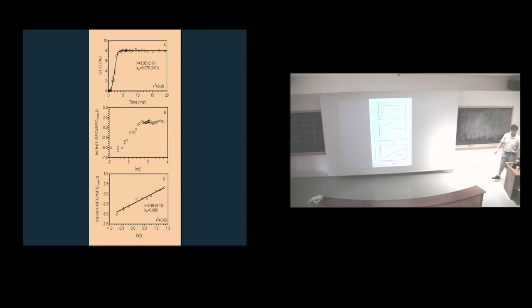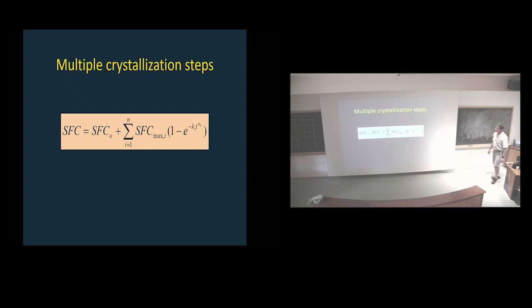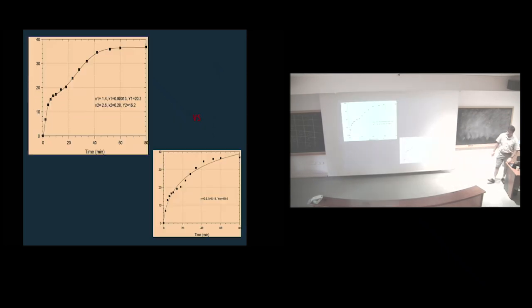And you can get, so this is another way people do it. FYI, I proposed at one point that we could have multiple crystallization events, so it's just a summation of Avrami's. And it actually does work quite well if you have something like this, for example, and you can get one species, two species present, each one with an N1, N2, K1, K2, and you can characterize that as well, as opposed to, it doesn't look too bad, right? You can put this through and people would believe you that that's good, right?